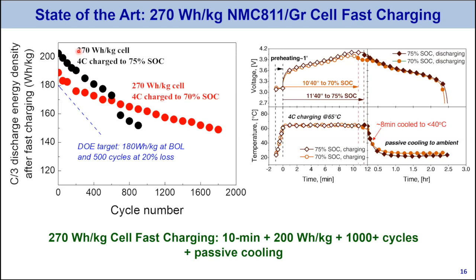Now, if we take the same cell, do the 4C charge only to 70% SOC, then the acquired energy is a little bit lower, not 190, but then you can cycle much longer, beyond 1700. Okay, so those both sets of data are now put together in comparison with the DOE target, shown here as a dashed line. Okay, so it's a practical method.